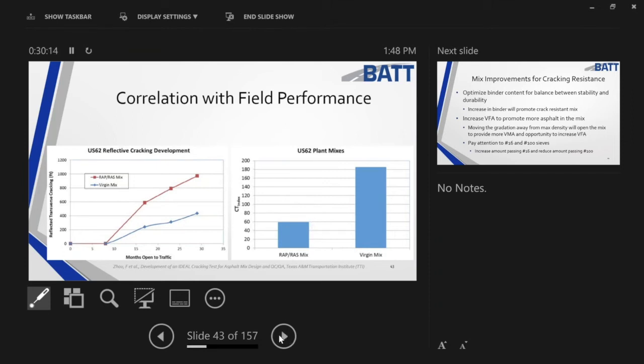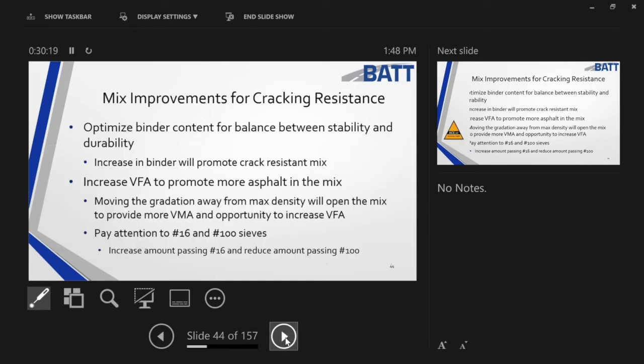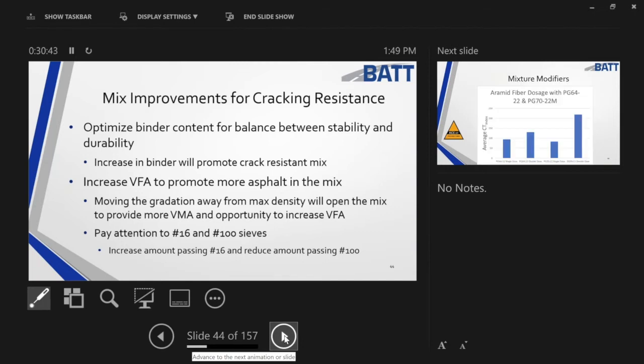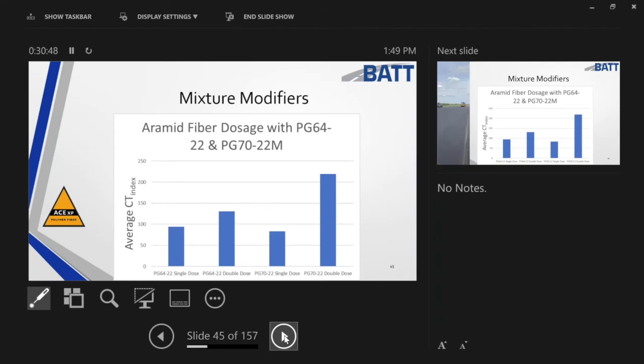Again, not to extend this out too long, but mix improvements as we begin to look at cracking resistance. We've got to optimize the binder between stability and durability. Like I said, I've made one that's really durable, but it was really unstable in the laboratory here. More binder promotes more crack resistance. Increasing voids filled with asphalt. Doing stuff such as lowering your dust to asphalt ratio or your dust proportion is going to help you, and so on. Now, let me show you some work we did here with the Aramid Fiber.